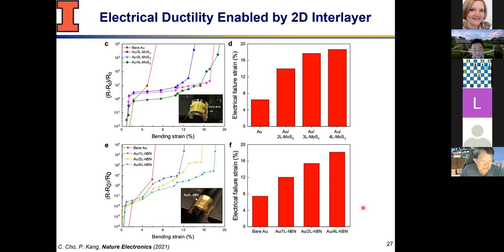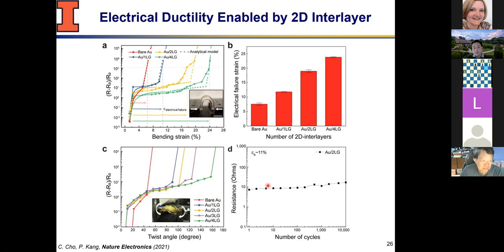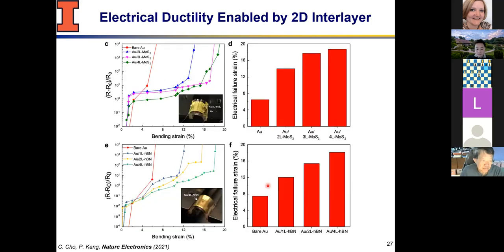If you were wondering, well, what if graphene being conducting, I think that's a fair point. And we concluded that conducting nature does help. If you compare what I'm showing you versus with graphene, so if you analyze all the data, by putting not a conducting layer, but a semiconducting layer, MoS2, or hexagonal boron nitride that's completely insulating, as an interfacial material of different number of layers, what you start to see is the similar behavior to that of graphene under bending. So we think it's primarily due to this interesting fracture control, or fracture patterns that we observe, and subsequently affecting or enabling this interesting electrical behavior by having this interlayer system.